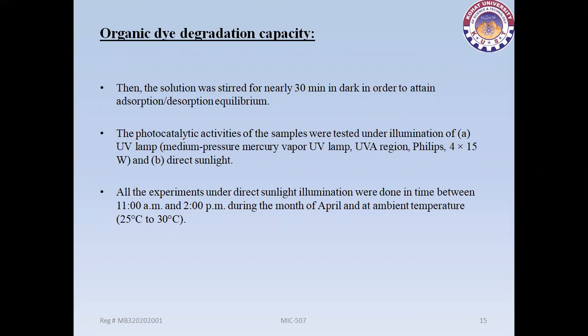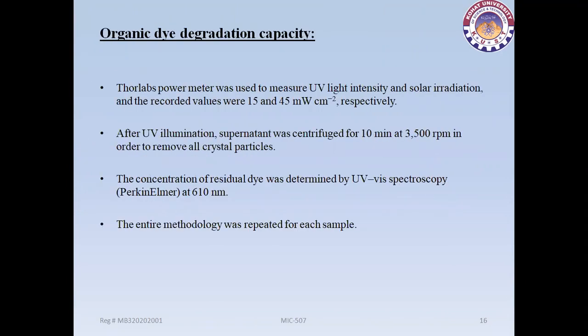UV lamp, UVA region, and direct sunlight. All these experiments under direct sunlight illumination were done between 11 a.m. and 2 p.m. during the month of April at an ambient temperature of 25 to 30 degrees centigrade. A Thorlabs power meter was used to measure UV light intensity and solar irradiation, and the recorded values were 15 and 45 milliwatts per square centimeter respectively.